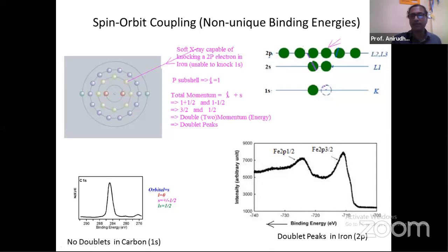So I made a point that when it is emanating from an s orbital, when L is equal to 0, let's see what is happening. When L is equal to 0, the total momentum will be equal to 0 plus S. So you will get 0 plus half, which is equal to half, and 0 minus half, where the magnitude is still 1 by 2. So in that case, there won't be two different values. There is one unique value. So you will get only one peak, corresponding to the binding energy for an electron which is emanating from an s orbital. If it is not from s, it could be from p, d, f, etc.